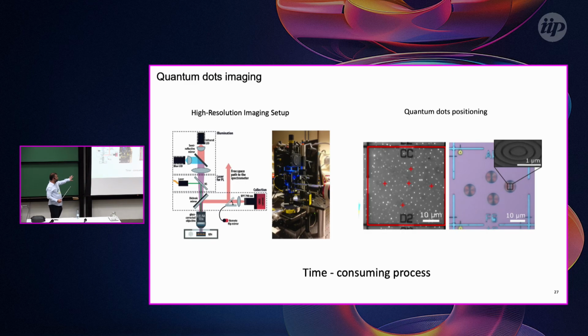If you have some markers, you can position and save the position of these quantum dots. And the nice thing about this kind of approach is that in general, you do not do this randomly. First we measure the quantum dot by photoluminescence. We check if this quantum dot has good optical quality, let's say if the fine structure splitting is small or the linewidth is small. And after checking this, we save the position. And after saving the position, you can make the bullseye structure around the quantum dot.